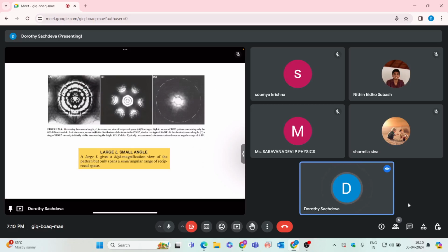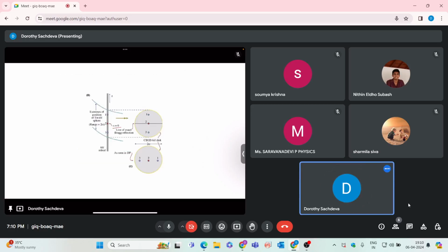This we already discussed, that S equal to 0 will be the line of exact Bragg reflection, and you will have your positive and negative values of S where your diffraction spot would be visible, because of the relrod. Even if your Ewald sphere is passing through this direction instead of this exact point, you will also see this diffracted spot. Also, we'll discuss a little bit about thickness fringes.